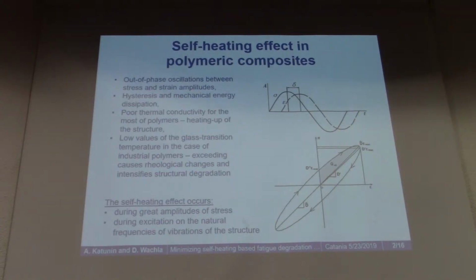If we talk about the self-heating effect, the genesis of this effect is in the viscoelasticity of polymers. Since we have out-of-phase oscillations between stress and strain amplitudes, we have a difference in phase, and it results in energy dissipation. Most of this energy is dissipated as heat, and in the case of polymers, we already saw a presentation at the beginning about heating in steels. So here, these heating phenomena are much higher in intensity.